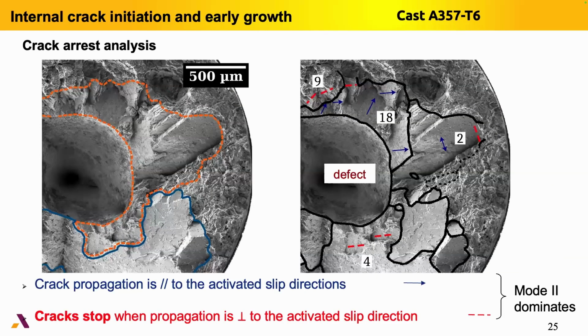So this is also an interesting point that we can see here. A detailed observation of the fracture of the specimen, after the cyclic loading and fracture by quasi-static loading, shows us that the crack propagation was parallel to the activated slip systems, but the cracks were stopped in the grain where the crack propagation becomes perpendicular to the active slip system that is in front of the crack. So it is interesting to understand why the cracks can stop. And it shows also that most of the propagation is done in mode 2.